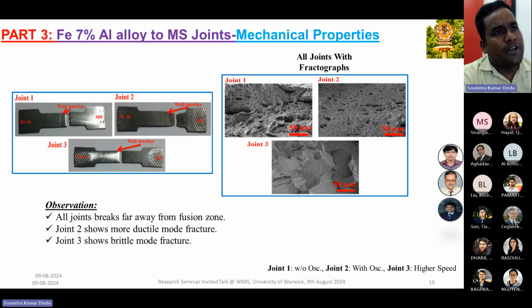And then we did the fractograph study, that is the SEM fractograph, to know which type of fracture surface is coming. In case of joint 3, we saw that this is a brittle mode of fracture. But in case of joint 1 and joint 2, we found a cup type of fracture, or dimple type of fracture, that is the ductile mode of fracture.